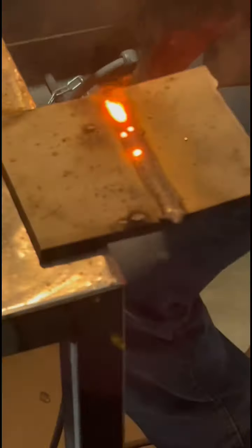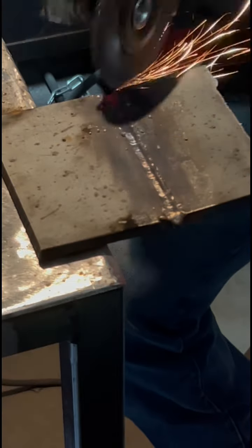Matter of fact, it's still going to be incomplete penetration, but the point of this is to show you that you are better off just doing a straight stringer without tacking, even if you don't get penetration, versus doing that little tacking method. So I already did that, just brushed it off. Now I'm running the hot pass or the fill pass, just covering it with some 1/8" 7018. Brush that off, and then I'm going to cap it with a single bead, weaving it back and forth.